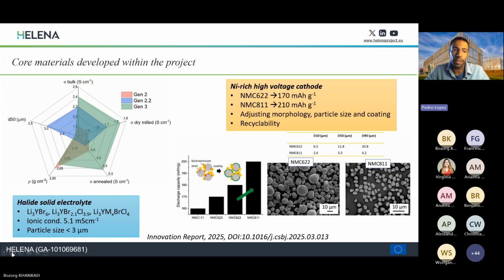We've also worked on decreasing the particle size of this solid electrolyte, as that is key to ensure high performance of the cells and good contact with the active material particles. And so, in these different generations of halide electrolytes, we've finally been able to target an optimized composition that is going to be used in the final devices.